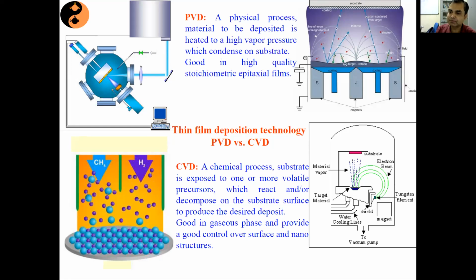So in physical vapor deposition, we are using a physical method to vaporize the material. Now we can ask ourselves, what are those physical methods to vaporize the material? The easiest answer that comes to our mind is that you simply evaporate it, you heat it. By heating, we can get the evaporation done. So if you have iron or tungsten, you just heat it, so that when that heat energy overcomes the bond energy between the different atoms, those atoms start evaporating. And then you collect those evaporants on a given substrate. That is how you get the deposition done by the physical method.